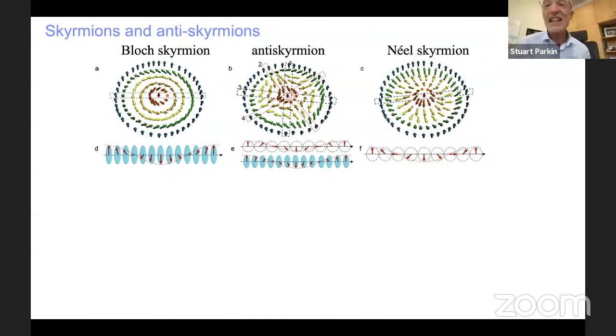So if you look on the right-hand side, you can see it's actually been found in only a small number of systems, until recently only in insulating systems at low temperatures, a Néel skyrmion. This Néel skyrmion is closely related to the chiral domain walls I discussed in Racetrack. In this case, this circular boundary consists of a magnetization that's rotating from the perpendicular direction on the outside to the opposite direction on the inside, and the magnetization rotates in a plane along the radius of the skyrmion. That's a Néel skyrmion. But in the Bloch case, the magnetization rotates from the up to down direction in a plane which is perpendicular to the radius or along the tangent of the skyrmion. I think you can see that in these cartoons.